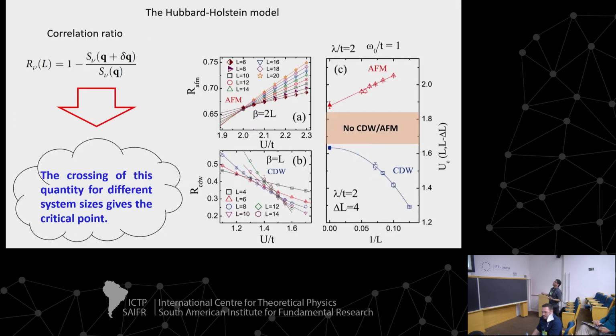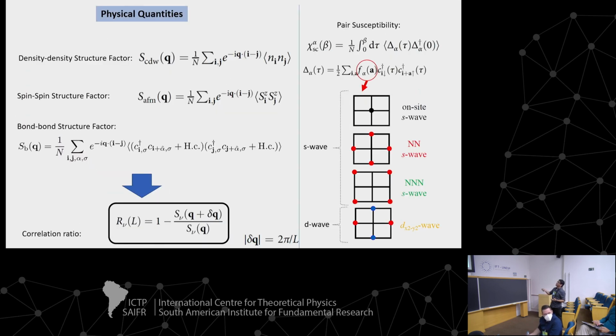So let me come back here. What I analyze is basically this quantity, the susceptibility of pair formation, and the divergence of this quantity gives us the answer. But my analysis at this point has sign problems, so it's a mess. What I found is that S-wave, in particular, sorry, it's not this one, it's this one here, the next-nearest-neighbor S-wave, what people call S++. There are many flavors of symmetries, but this one is dominant and diverges. This is what I found.